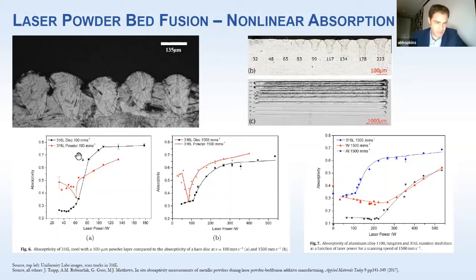I believe it's a 100 micron thick layer. You can see you have far more absorptivity initially with lower powers. This again is a 100 millimeters per second scan. The reason for that is you have a curved surface. Your particles have curved surfaces. There's higher absorptivity as a function of porosity of the powder itself. So the particles versus the space between them. That's what I mean by porosity.